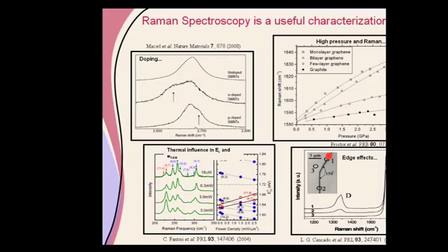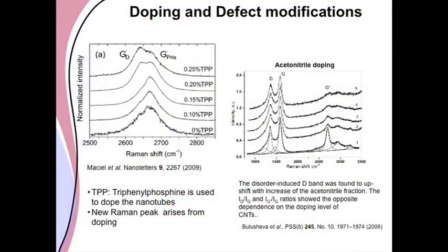But symmetry tells you that the zigzag edge should have a vanishing matrix element. So if the sample had been a really good sample, with a perfect edge, with no defects, then this signal here should have vanished. Well, it's pretty small, so that's the best at that time. This is pretty old work. It's 7 years old, and we make better edges now, but that's just to show you an idea about edges, how you could study them.